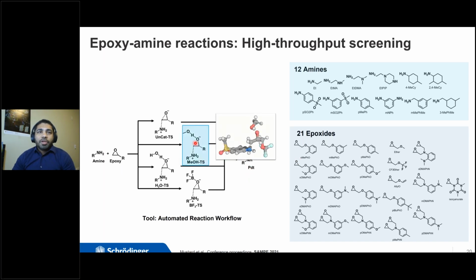And we can look at what transition state results depending on what catalyst is being used, and also the corresponding activation energies required. Depending on whatever R group is used for the amine or epoxy, the energies would be different. So we can change the R groups and then control the reaction energies for these systems.